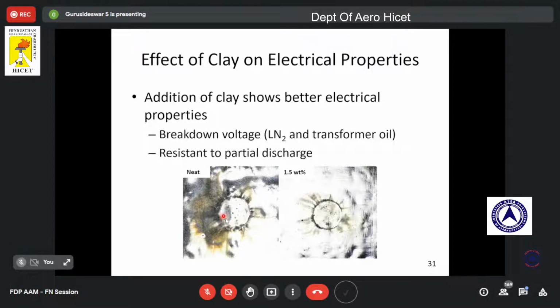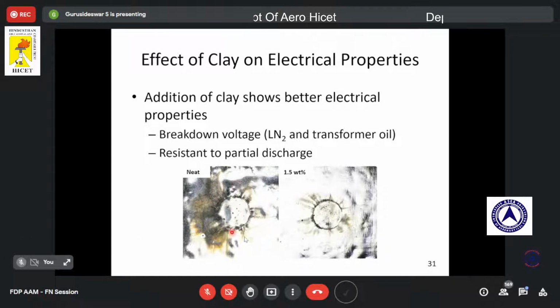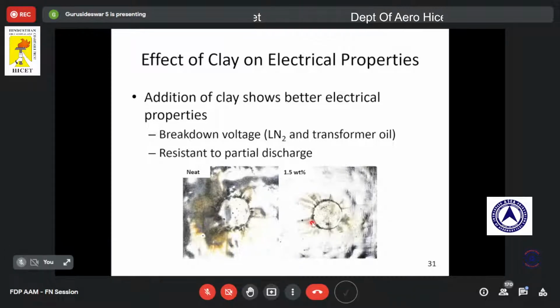One can observe that the sample was subjected to high voltage, around 5 to 10 kV. You can see the photograph after the application of electric voltage. The neat sample has a major damage. For the sample having 1.5% clay in epoxy, you can see minimal damage. So the idea is that addition of clay in epoxy leads to better electrical properties. This is what we observed from this breakdown voltage test.